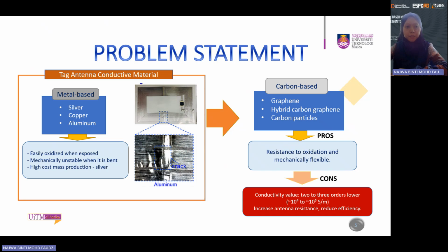So the problem here is regarding the conductive material of the tag antenna. So normally the conductive material or the conducting elements that have been used are based on metallic materials such as copper, silver, and also aluminium. While these materials exhibit excellent electrical conductivity and mechanical properties, they have some limitations. For copper and aluminium, they are easily oxidized at ambient temperatures and also can be cracked upon bending. This can be seen here. It can be easily cracked upon a few times of bending.